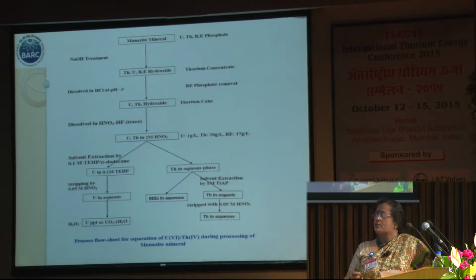So based on these two observations, we extrapolated it to the monazite source, and with monazite we checked the conditions and developed a flow sheet. Up to this point, there is sodium hydroxide treatment, then dissolution with HCl for rare earth phosphate removal, and then the cake is dissolved in a nitric acid HF system. HF will be in trace quantities, and now it has become a nitric acid solution.